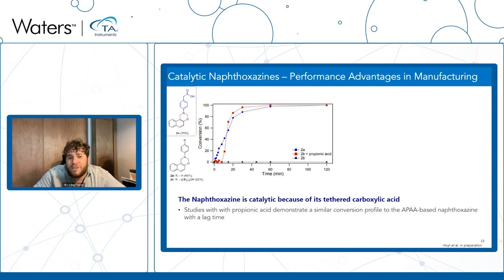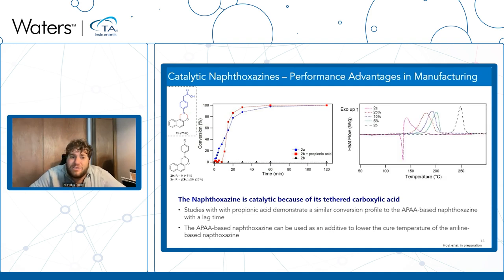When you take your petrochemical reaction and add propionic acid, so it looks like this bio-derived resin, you can get your cure to complete within 2 hours. So it is this catalytic moiety versus the petrochemical material itself, which doesn't cure. Where I was getting ahead of myself on the last slide is that, as I said, this 2A material, this bio-derived naphthoxazine, is a solid, so it's not ideal for applications. But we can use this as an additive in the petrochemical derived material, and we can lower the temperature of cure for the petrochemical derived material.